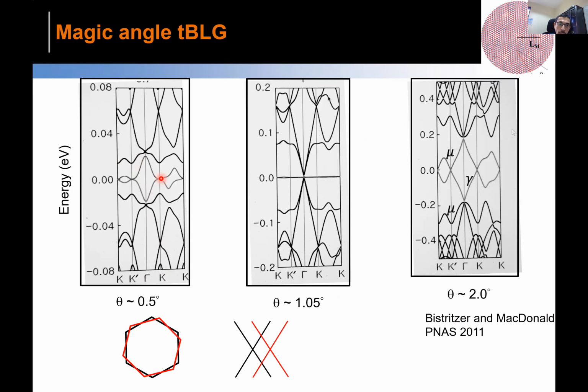So you can see, as I change the momentum, the energy is also changing quite rapidly. Similarly, at 2 degrees, if I change the momentum, so I guess you know all these gamma, K directions, the symmetry points of your Brillouin zone. If I change along those directions, you see the energy changes with momentum quite rapidly. However, for 1.05, this paper shows that there is a flat band. You see this innermost one, the energy remains almost constant with momentum. So it doesn't change.